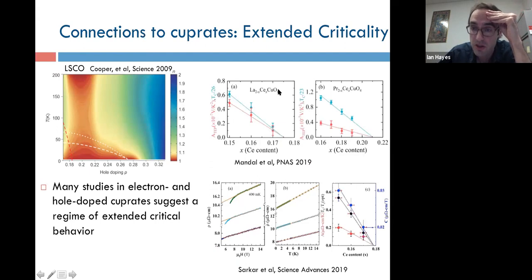Electron-doped cuprates, where you can measure the low temperature resistance fairly directly, also show a T-linear behavior that vanishes near the overdoped side. And those same films also show a logarithmic upturn at low temperatures that's often characteristic of quantum critical systems, that diminishes and vanishes at the same point where superconductivity does at the overdoped side.